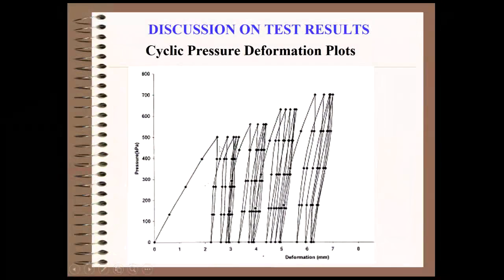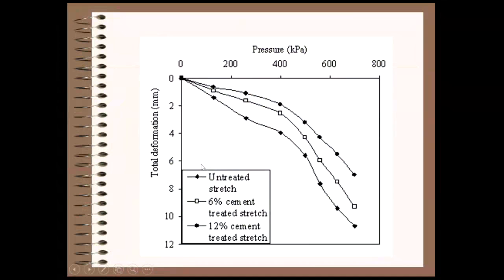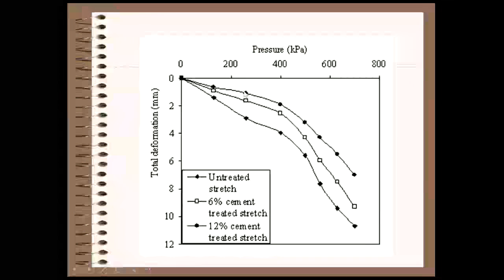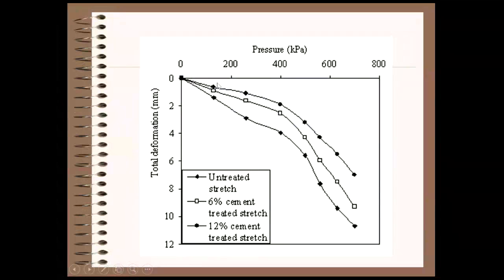The cyclic plate load test, the data presented like this. See how we have done? Only one pressure repeatedly increased until here a loop is formed, no more settlement. Okay, until we reach this no more settlement loop, the testing is continued for every increase in the pressure. Ultimately, from this load settlement patterns, we captured the elastic deformation and also the total deformation. From this, the total deformation versus pressure plots were drawn. Interesting, you see, when cement stabilized, the deformations are very insignificant, within one, just like that for these pressures.